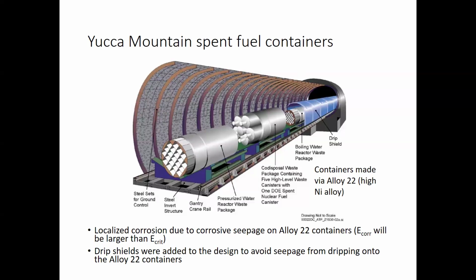So from a corrosion standpoint, this is kind of the inverse of the Canadian scenario. In the Canadian scenario, you have reducing conditions, so you use up oxygen, and you're relying on your container not to form a passive coating. The reason for this is if it forms a passive coating, you can then potentially enter a pitting scenario. You can't get pitting unless you have passivation first.